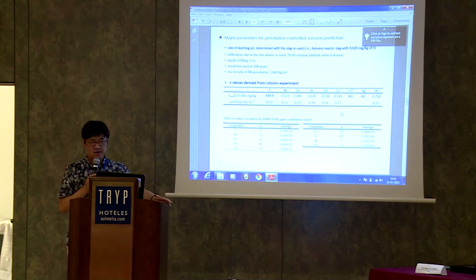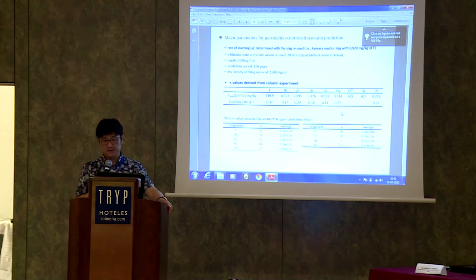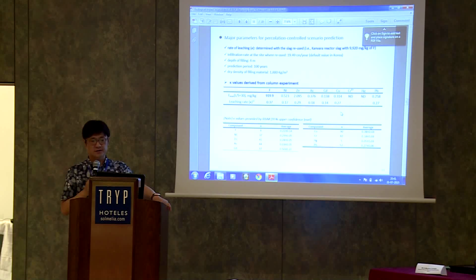So from the column experiment, the maximum leaching concentration of fluoride from the slag was about 900, and the kappa value was about 0.37. And the Dutch government provides some default values for the kappa values, including fluorine and some heavy metals. And as you see here, the kappa value that I derived in this experiment was about the highest.